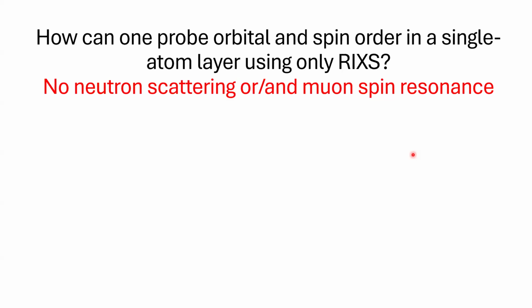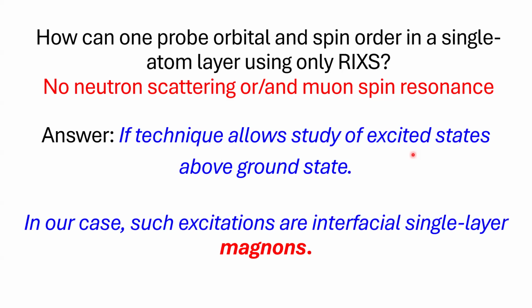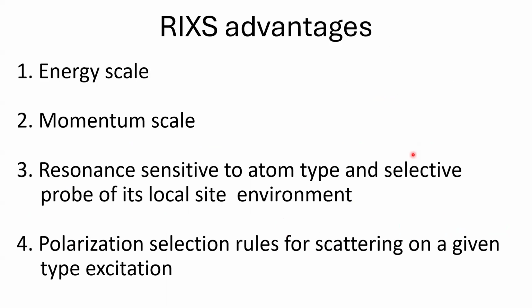How can one probe orbital and spin order in a single atomic layer using only RIXS? We did not use neutron scattering or muon spin resonance. This is possible if our technique allows the study of excited states above the ground state. If we have this excitation above the ground state, we can say something about the details of the ground state. In our case, such excitations are interfacial single-layer magnons. For this study, we use almost all RIXS advantages: energy scale, momentum scale, resonance sensitivity to atom type and selective probing of its local site environment, and polarization selection rules for scattering on a given type of excitation.